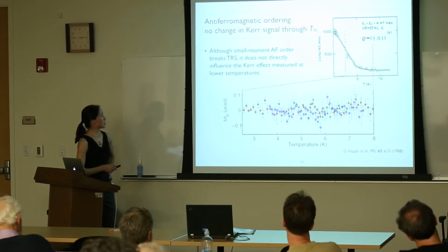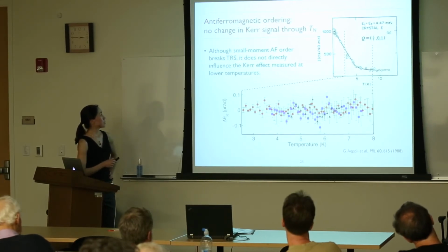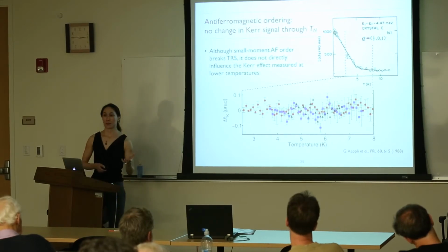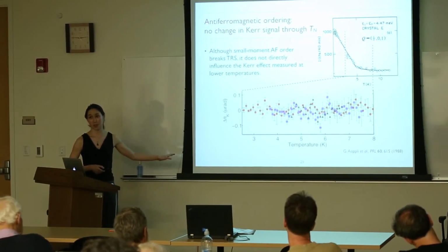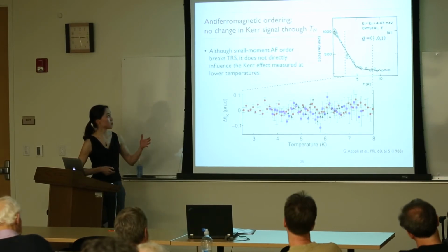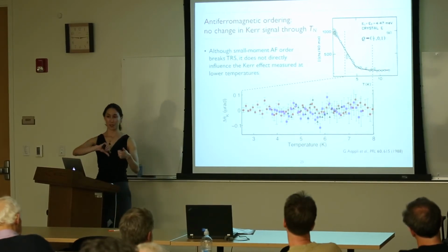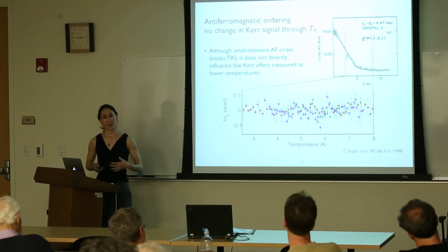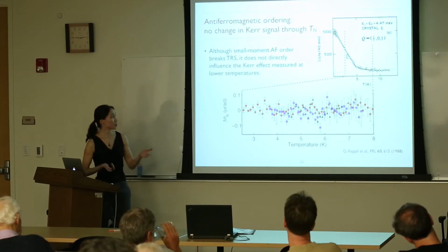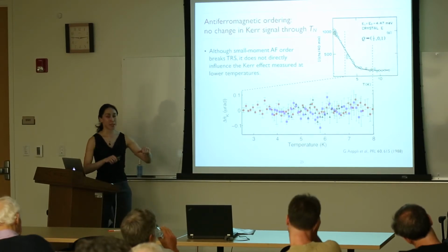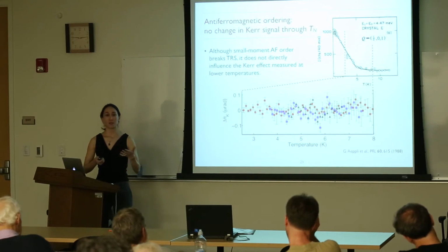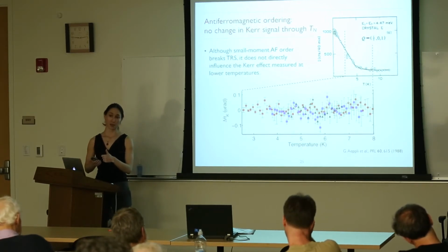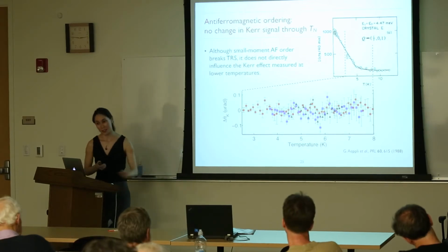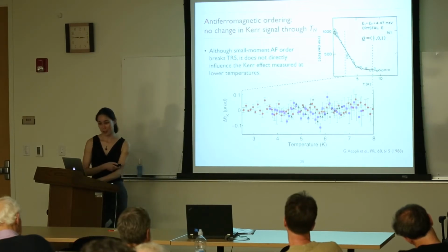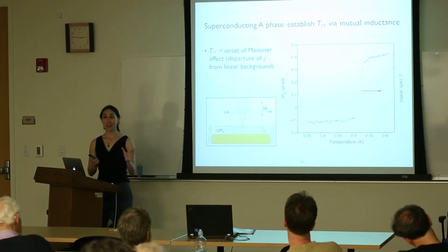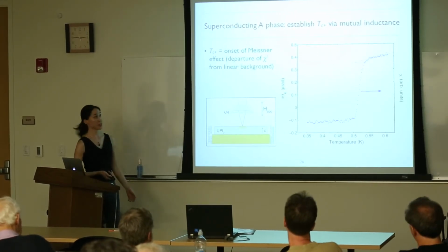So the important thing is just to say that even if antiferromagnetism does break time reversal symmetry, it doesn't seem to directly affect Kerr effect as far as we can tell. Again, this isn't a huge surprise. First of all, antiferromagnetism has moments that are aligned opposite to one another, and we should be sensitive to some net moment developing in the material. Moreover, the moments lie in the AB plane of the material, and we should be sensitive to moments along the C axis. Nevertheless, this was an important thing to check. People would be angry with us if we didn't, so there it is. So we can now confidently go to lower temperatures and see what else there is to see in this material.